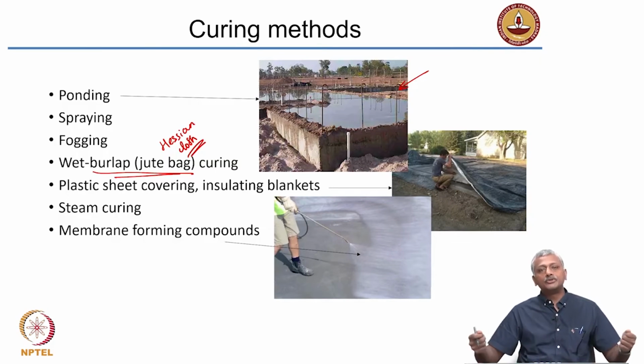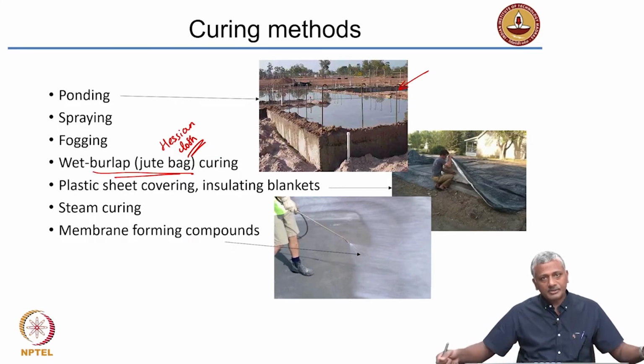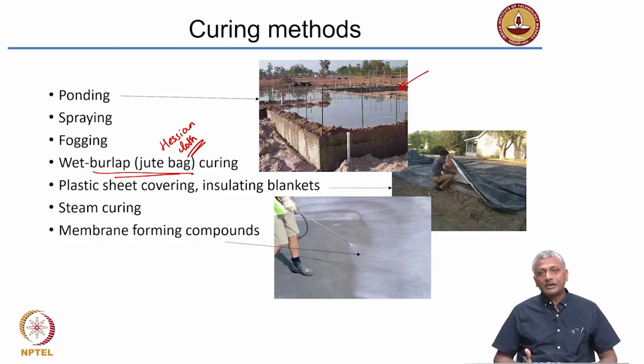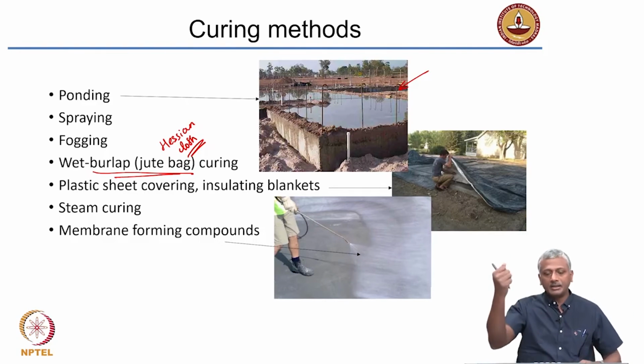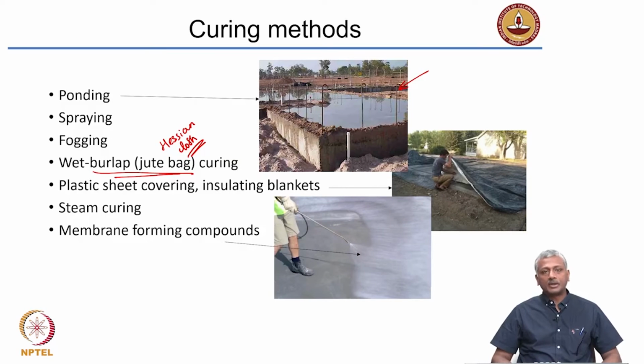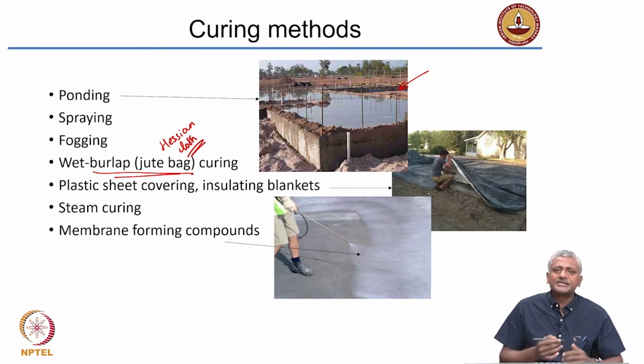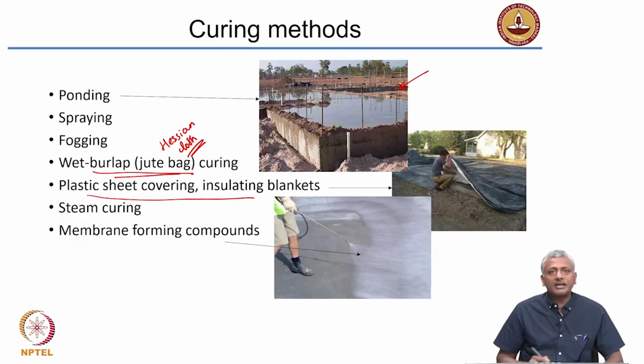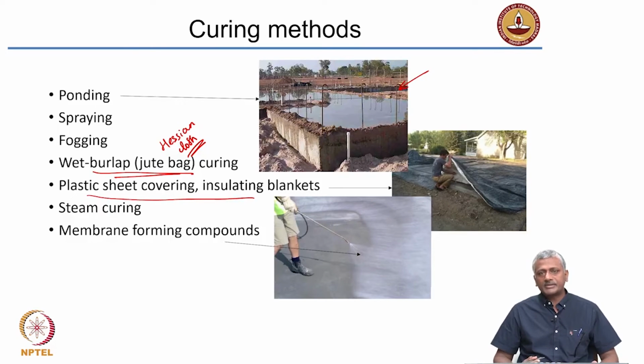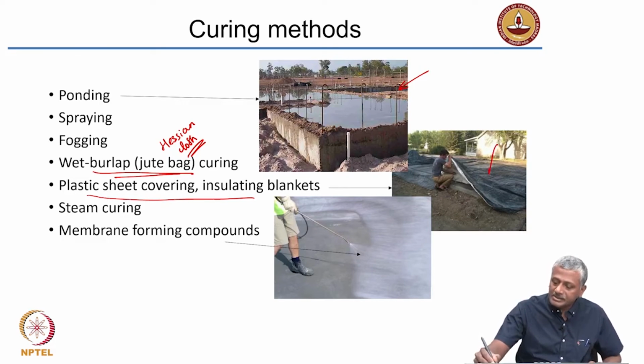So you have wet jute cloth, which is kept on the surface of the concrete. But you have to take care to ensure that this cloth is always wet. Otherwise, if the cloth dries out, the concrete also will eventually dry. In many instances, you will find that columns especially are covered by wet jute cloth type curing. But you need to ensure that the jute cloth is wetted from time to time to maintain the wetness properly. In some conditions, it's enough to put some covering on the top surface to restrict the evaporation, for example, plastic sheet covering that reduces evaporation, or insulating blankets like this.